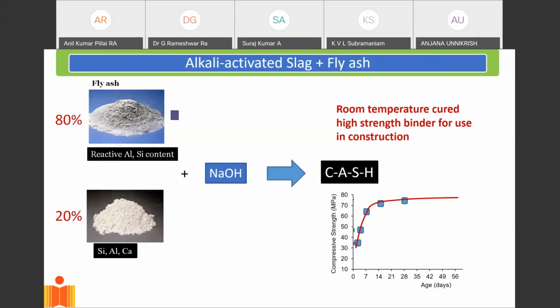To overcome the problem of requirement of temperature, where even using only fly ash, we need a temperature of about 40 degrees, we've developed a room temperature cured material, which can be cured at room temperature, about 27 degrees, by blending fly ash with slag. So we take fly ash and slag, then we optimize the binder, the sodium hydroxide and the sodium silicate that's needed, which gives us the calcium alumino-silicate hydrate.